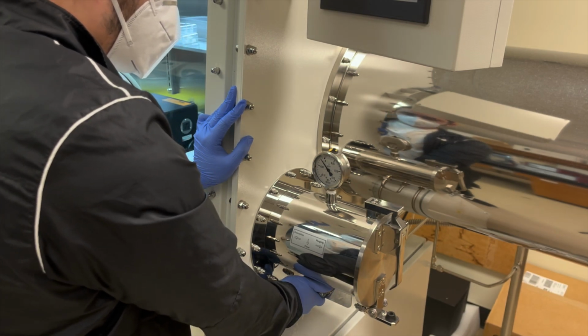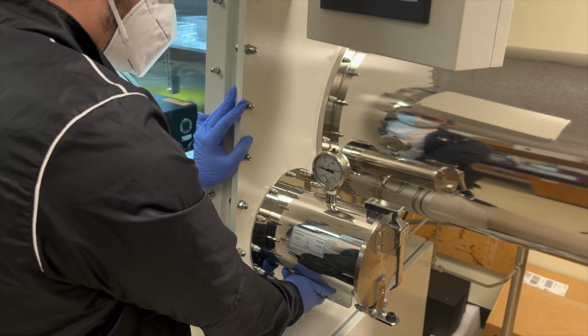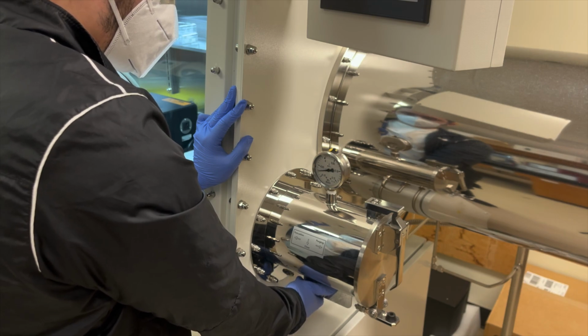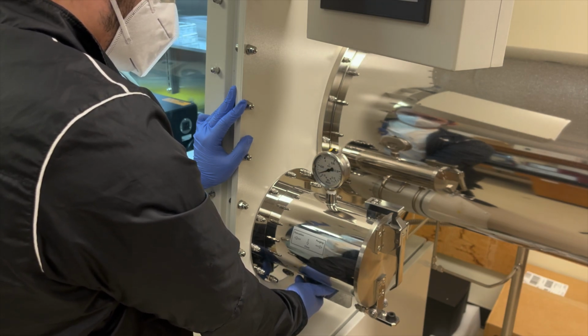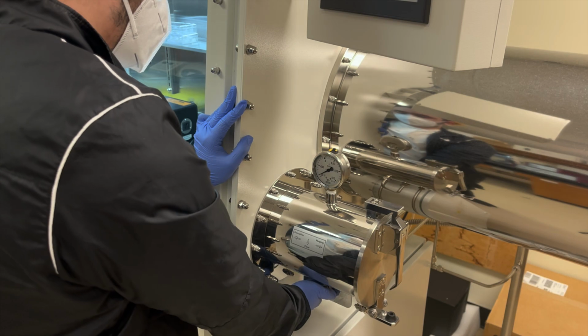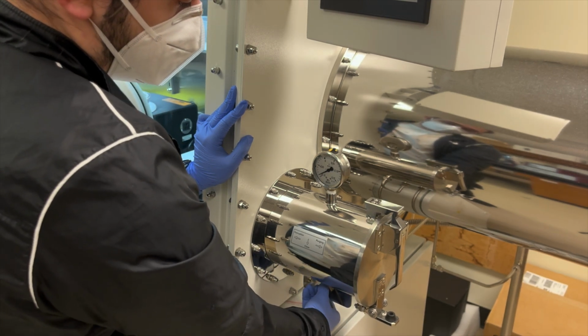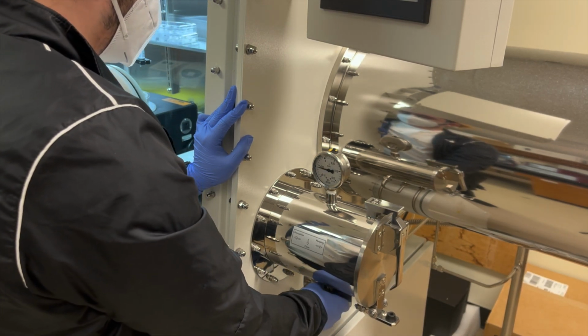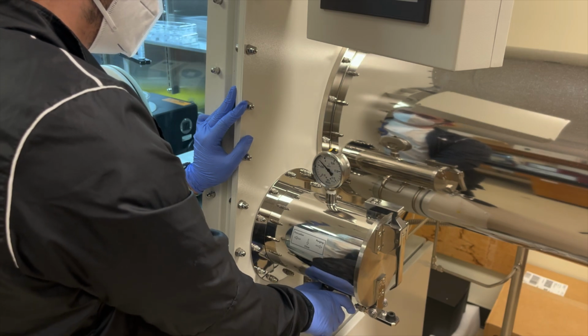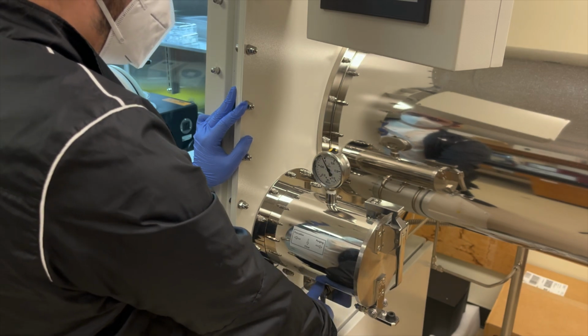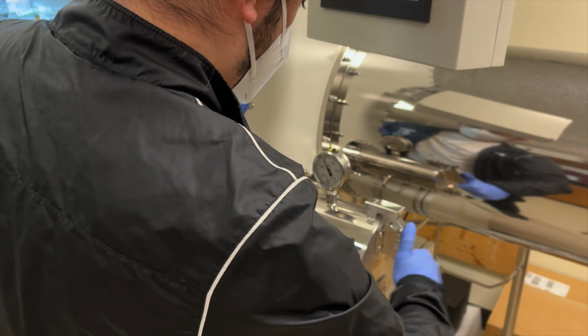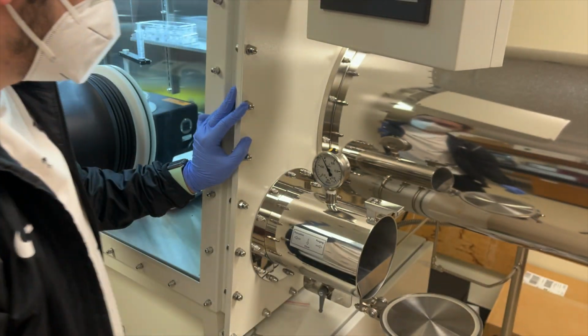In order to assemble our battery, we must transfer our components into a vacuum glove box. The glove box is moistureless and filled with argon, which makes for a non-reactive assembly environment. Before we put our electrodes in the chamber, we must evacuate and then purge that chamber 3 times. After the 3rd time, we may open the chamber and place our electrode.